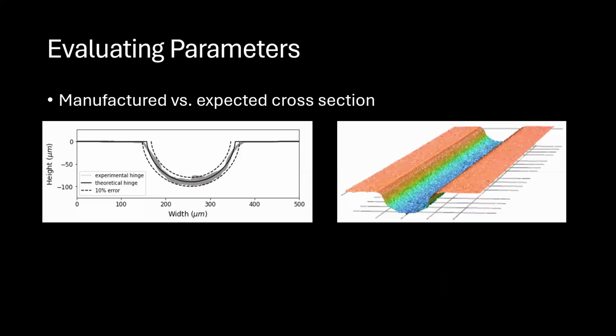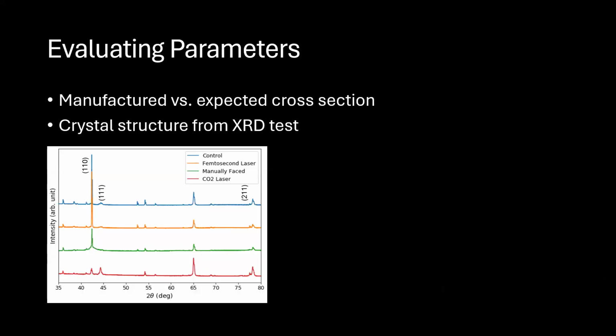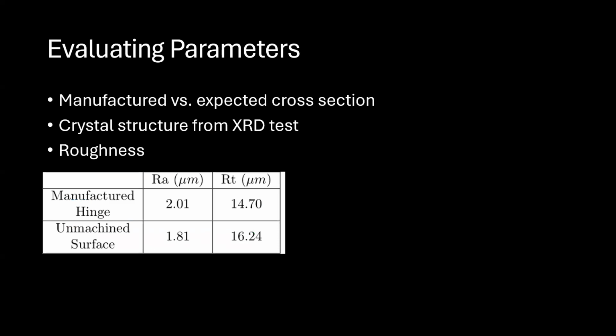We evaluated our laser parameters 4 different ways. First, we compared the cross-section of a manufactured hinge to the theoretical cross-section and found they matched up well. Next, we performed an X-ray diffraction analysis to confirm that the femtosecond laser did not alter the underlying crystal structure by transforming austenite into martensite, which would degrade the nitinol's superelastic properties.